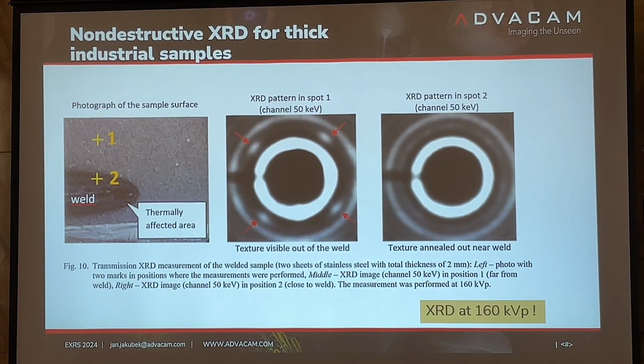And if you do rolling, you would orient the grains inside of the sample, and then actually you would not get a circle, because not all the angles would be happening with the same probability, but you would always get this kind of maxima here. So one sheet was rolled in this direction and another one in this direction. So having them both welded like this, you have this kind of 4 peaks here.